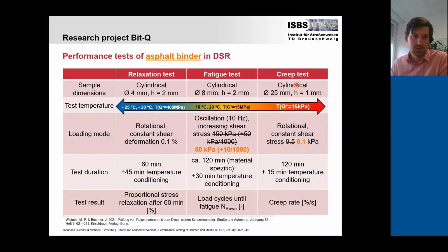We also extended the performance test in the DSR on the binder level, just to compare also the effect of the binder. We slightly varied it. For low temperature, we used an identical test setup. For the fatigue test, we slightly reduced the shear stress increase, so this step experiment, and also for the creep test, we reduced the shear stress. We also reduced the test duration here. Unfortunately, I forgot to change it, so it's only 10 minutes.